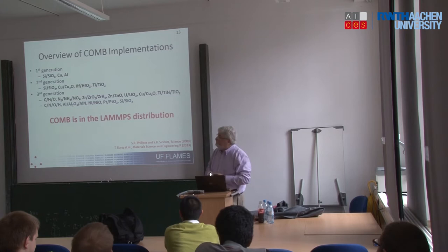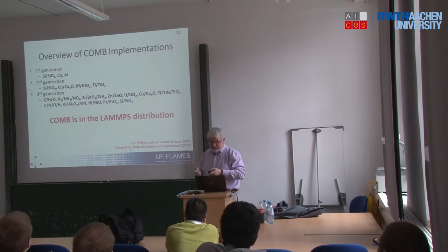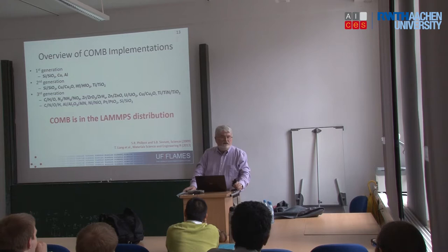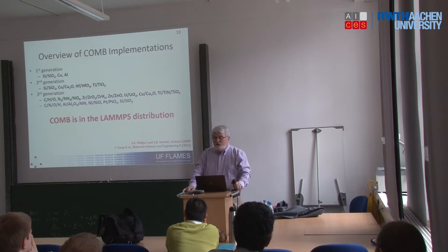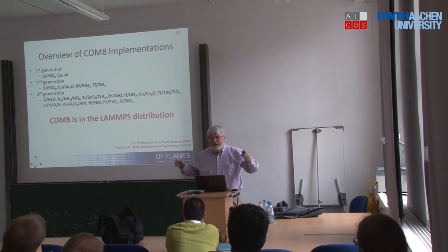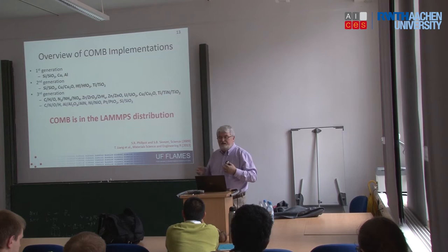We've done that. And there's a slightly different philosophical take we've taken. As I said, the oxygen interactions, for example, are all compatible across this whole range of materials. What he tends to do is he has a problem he's interested in. So maybe he's interested in two problems involving carbon, hydrogen, nitrogen, oxygen. One may be an explosive, for example, but one may be a biomolecule. What he'll do is develop a parameter set for each of those problems, which are different from each other, and that won't play together. So he focuses very much on the problem at hand to get the best fit. We focus on getting more transferability, but there's some sacrifice of accuracy for any given problem when you do that.